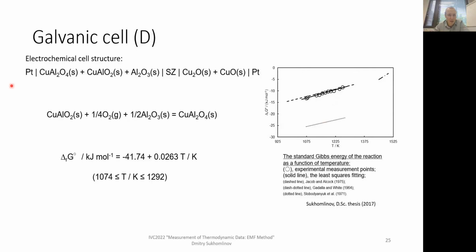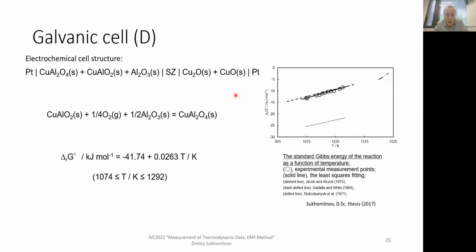And then the last reaction with two ternary phases and alumina. And again, another solid reference electrode. So by combining measurements from these 4 different galvanic cells, we were able to calculate Gibbs energies of formation of our ternary phases.